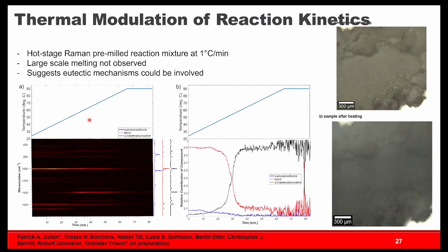And so to explore that, we took a pre-milled reaction mixture. We basically took the two components, milled them for 30 seconds, put them on a hot stage, and then applied a linear temperature ramp. Now, this isn't quite the same profile that you expect in milling. It's slightly more exponential, but as a first order approximation.